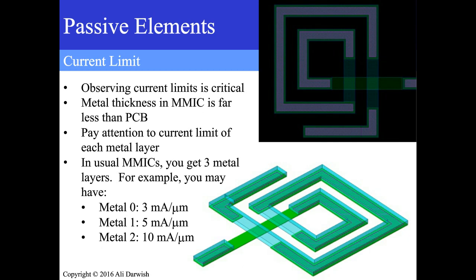Current limit is an important issue because when you do printed circuit board, that's not a big consideration. When you do printed circuit board, let's say you use an ounce of copper. Well, an ounce of copper is like 35 microns thick. And so typically you don't run into current limitations even for narrow lines. But for MMICs, and I'm showing here the picture of an inductor, as the metal goes under the air bridge, you're using only one layer of metal. And that one layer is usually the bottom metal, and that bottom metal can pass a limited amount of current, so maybe only 3 milliamps per micron.